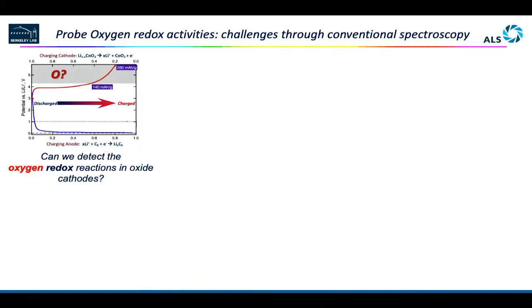However, electrochemical process is a crude process in which you can just drag the electron out, whether the system likes it or not. So it really drives the system into a different fundamental ground state. That is very important because, as I said, the key thing here is which electron state you are working with when you go to the high voltage. And the question it triggers in chemistry language is always a straightforward one: is the electron pulled out from the transition metal or from the oxygen? And this is also a safety issue. If you pull out the electron from the transition metal, it is a relatively stable structure, and then cycling is more stable. But if you pull out from oxygen, all different kinds of structural collapse and oxygen release happen, I will talk about that a little later, and all the safety hazards also come in. So that's just a very general impression of the thought.